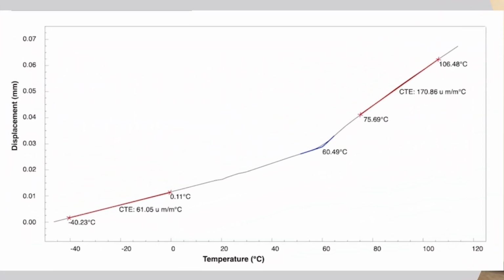This is the graphic result of a TMA. At the low temperature portion of this graph on the left, you see the pre-TG CTE from -40 to 0 degrees C of 61 ppm. As the temperature increases to the right, we see an inflection point on the graph at about 60 degrees C. This is the TG. Below this temperature, the polymer is considered a rigid polymer, and above this temperature, the polymer is a soft, pliable polymer.